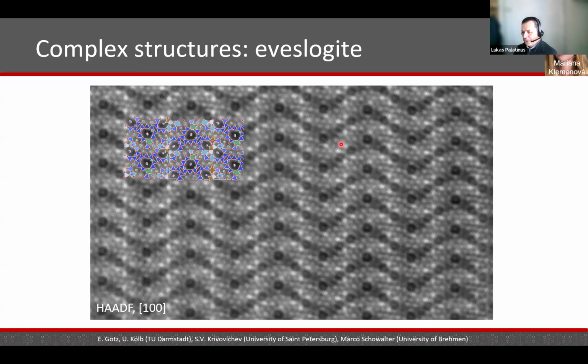In general, the smaller the crystal, the better. In terms of dynamical effects, it's the thickness that plays a role. So the thinner the crystal, the less chance there is for multiple scattering, so the less dynamical effects there are. However, even in nanoparticles as small as 10 nanometers in diameter, there are measurable and appreciable dynamical effects.